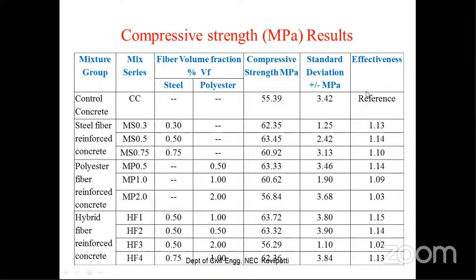And these are the test results, and you can see the test results of the 4 series. Please observe the last column of the table. From this we can understand the effectiveness of adding the fiber. Control concrete gives a reference value, and in the steel fiber series you can see the range is increasing. The increment is only from 10 to 13%. In polyester fiber it is a little bit lower, sometimes only 3% improvement. And in hybrid fiber reinforced concrete also, the maximum improvement is only up to 15%.